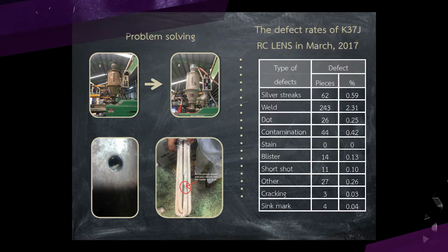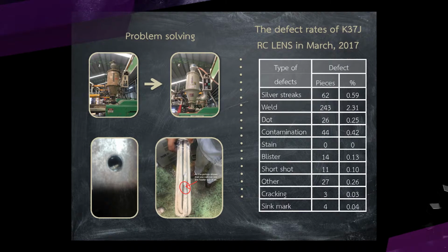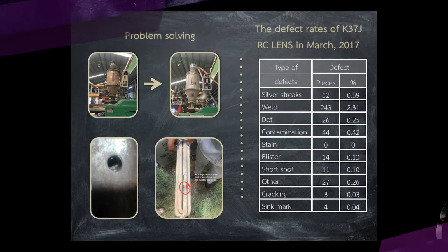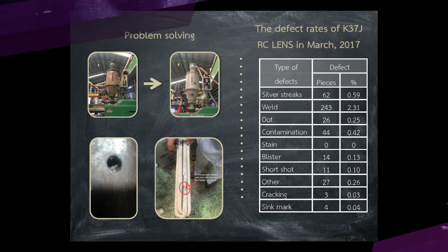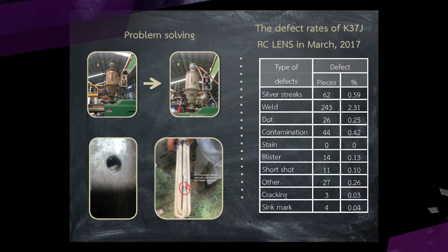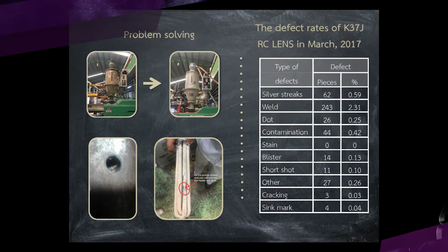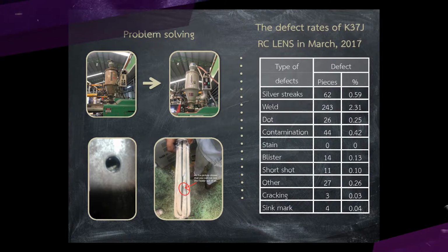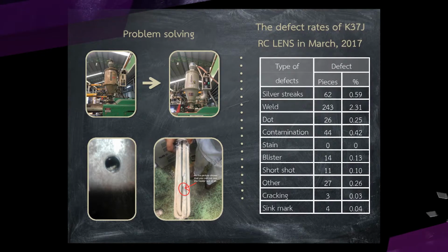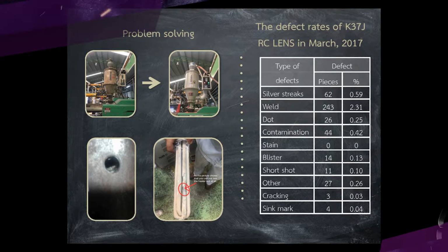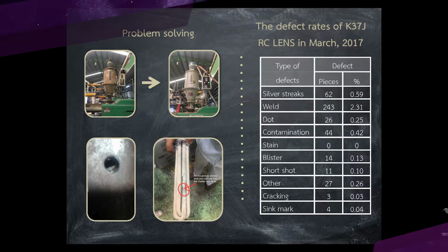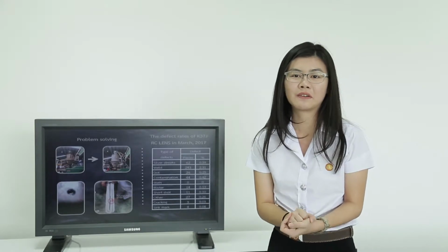And after the improvement, the defect rate of K37J RC LENS in March 2017 shows that the defect rate of silver streak decreased from 2.42% to 0.59%, while dot and contamination reduced to 0.25% and 0.42%. However, weld increases to 2.31% because the problem of water system has not been solved yet. And the overall defect rate of 2016, which is 12.21%, was reduced to 4.53%, which is lower than the yield of 5%.